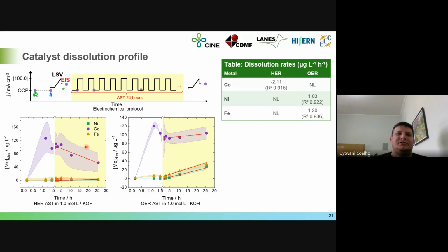For hydrogen evolution reaction, the cobalt is redeposited on the catalyst surface, and the nickel and iron stay at the same levels. So there is no dissolution. Of course, the catalyst is negatively polarized, so these metals in solution just tend to deposit on the catalyst surface. And it happens with the cobalt, for example. All the cobalt dissolved during the open circuit potential is just redepositing on the catalyst surface time by time. But for oxygen evolution reaction, we can see that the cobalt is stabilized during the accelerated stress test, but the nickel and iron are constantly dissolving over time.